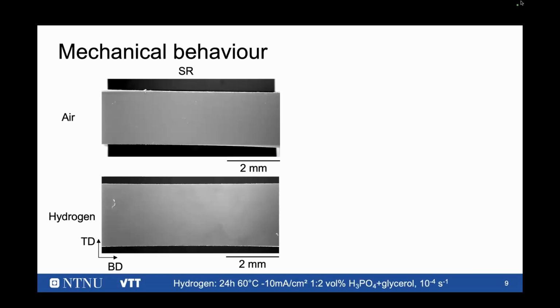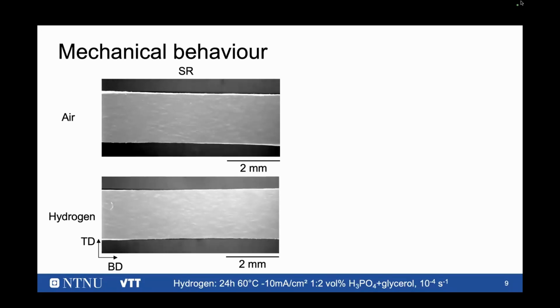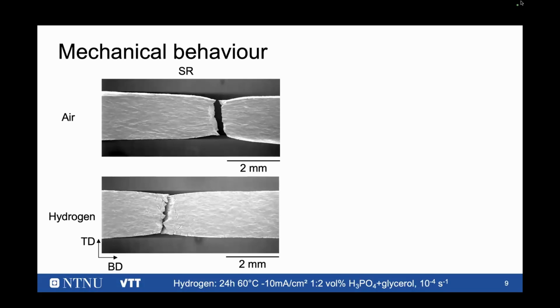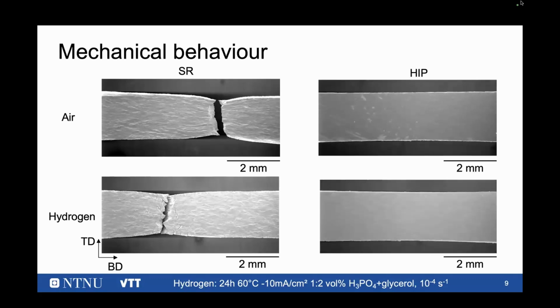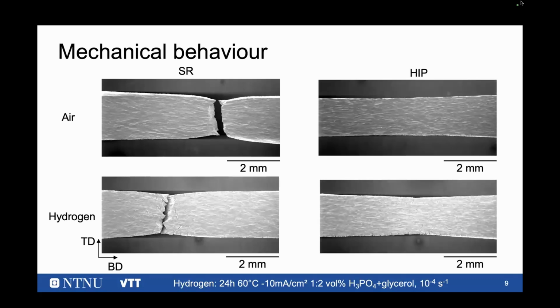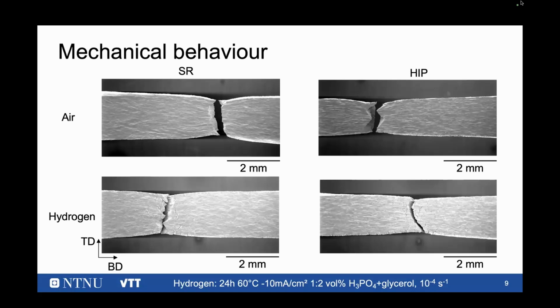Then we went to the mechanical testing. Well, it's quite what we expected. This is for the stress relief condition. On top, you see the air condition. On the bottom, you see the hydrogen condition. And as we expected, the hydrogen condition fails earlier, and you also see some cracks present on the fracture plane. The same holds true for the HIP condition. Again, here there are even more cracks on the fracture plane, on the normal plane here, and it fails earlier as well compared to the air condition.